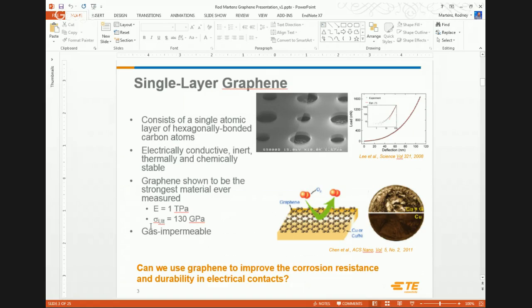Talk a little bit about graphene just fundamentally. I would argue graphene, carbon nanotubes, buckyballs, they're all still a bit on the upward swing of the hype curve, but if you've done any reading about the material whatsoever, I think you consistently hear that it's the strongest material that's ever measured. The modulus is on the order of a terapascal, strengths of 130 gigapascals. I've shown a couple of images here in the upper right, some work done by Lee and others where they etched holes in silicon, transferred some graphene sheets over it, and then used a nanoindenter to essentially probe the suspended graphene to get some material properties out of it. So you can see they're deflecting on the order of nanometers and applying loads on the order of nanonewtons to get these properties.